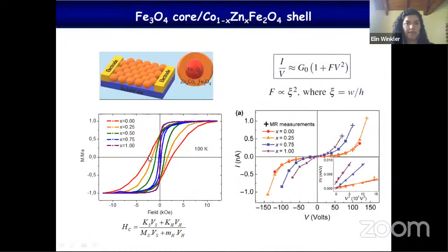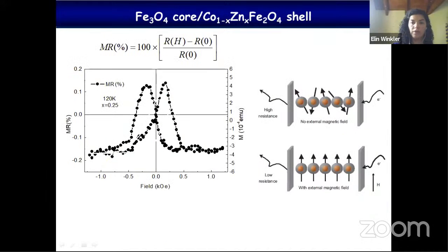I'm going fast through this slide, but you can observe that the coercive field, as expected, is systematically reduced when we replace the cobalt by the zinc. So the coercive field results from an average of the parameters of both materials. When we measure the current as a function of the voltage, we observe that this relationship is not linear; instead, it presents a dependence where I over V is proportional to voltage squared. That is the expected behavior for tunnel conduction.